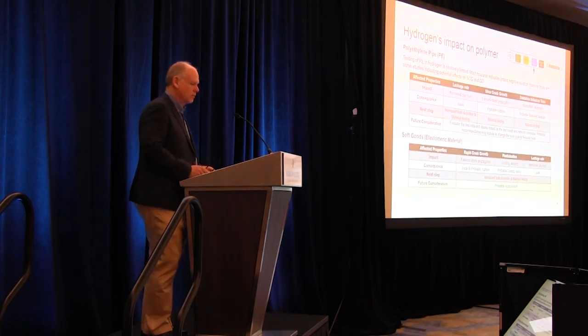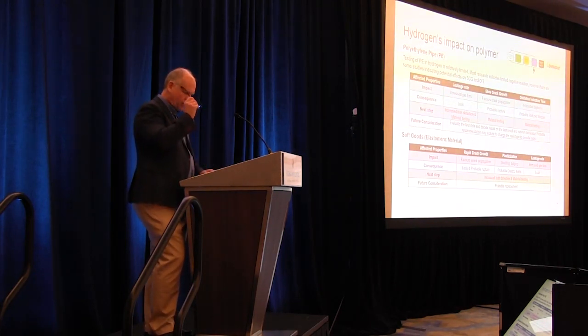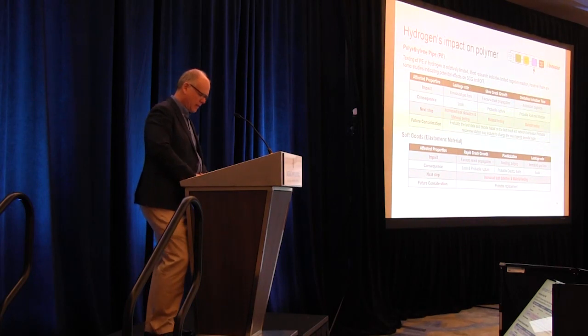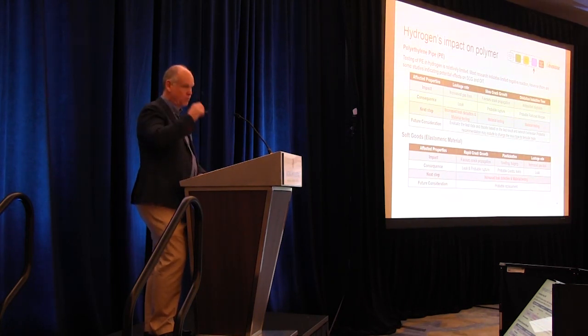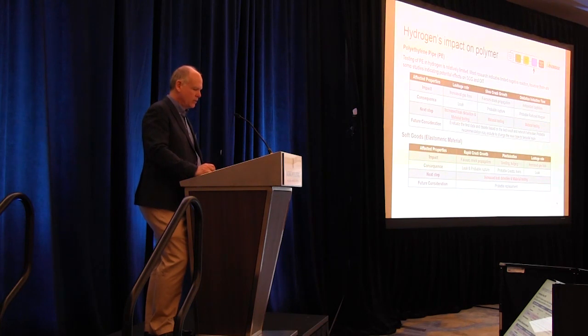The other materials that we're involved in, so polymers. There's two industry standard tests on polyethylene: slow crack growth and oxidation induction time. Those are sort of two standard polyethylene test results or test regimens. And that really looks at fracture crack propagation in plastics and the depletion of the antioxidants.